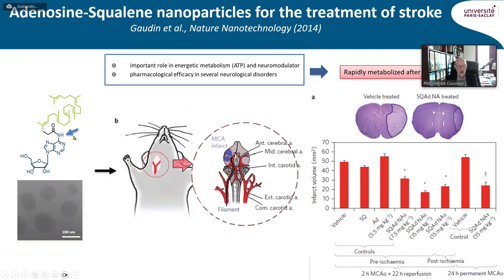And in fact, this is due, as you can see here, to the rapid deamination of the amino group of adenosine by the deaminases. And in fact, to protect the adenosine from this fast metabolization, we have linked here in green the squalene through the squalenic acid to the amino group of adenosine. And after putting the adenosine squalene prodrug into water, we obtained once again nice nanoparticles, spherical shape with a size of around 100 nanometers. And we have tested those nanoparticles for the treatment of brain ischemia by inserting, as you can see here, a filament in the right carotid of mice.